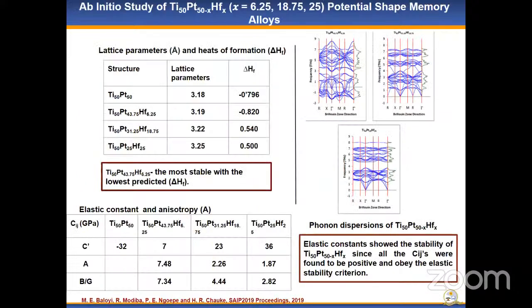The other success story here also was done by Mr. Baloi, who also used the same relation to do this calculation, relating the heats of formation and also looking at the phonon. So here you can see that when you do the doping, as he has done here with the hafnium, you find that at smaller concentrations, you may have a lot of vibration, but as you increase the concentrations, looking at these phonon dispersion curves, you see that now the negative frequencies disappear at higher concentrations, and that relates to what you see also with the heats of formation that have been calculated.